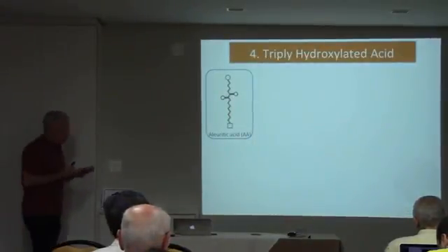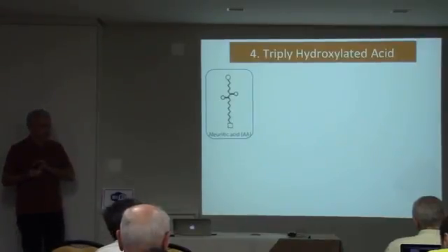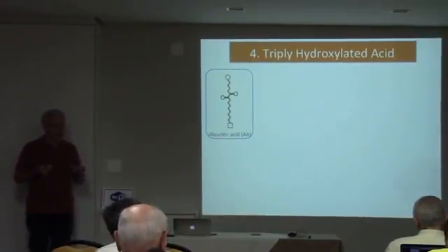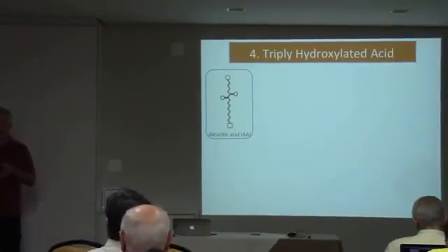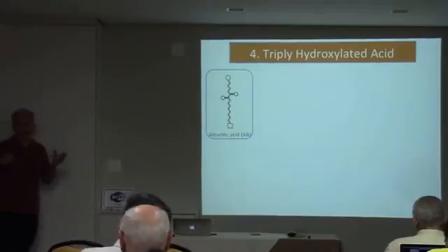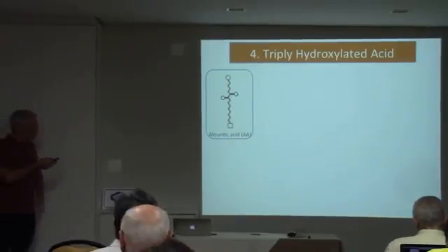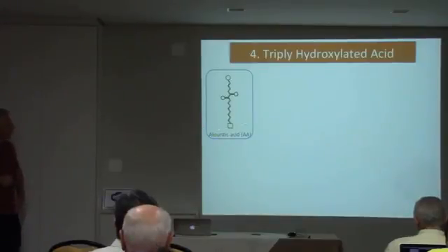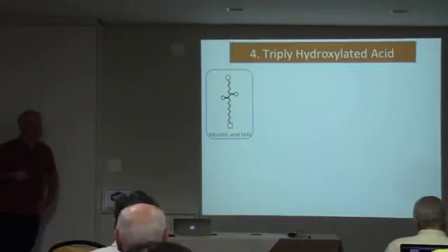Well, all these results help us to suggest an artificial monomer to create the biomimetic polymer. We used the aleuritic acid, which has the carboxylic group, the terminal hydroxy, the other hydroxy group, and an additional hydroxy group.